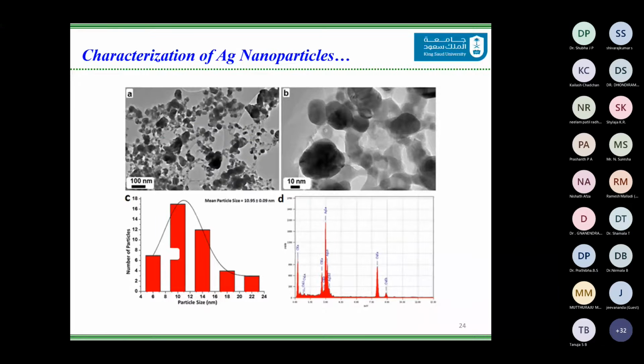So the TEM of these nanoparticles revealed that the particle size is between 10 to 20 nanometers. And the nanoparticles are well distributed. However, you will see some very minute chunks where agglomeration is still present. The EDAX also gave us the confirmation about the presence of silver as a major element. However, there were other elements that were also found in the EDAX.